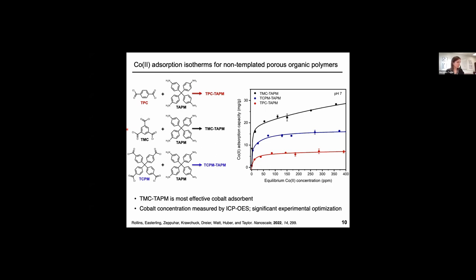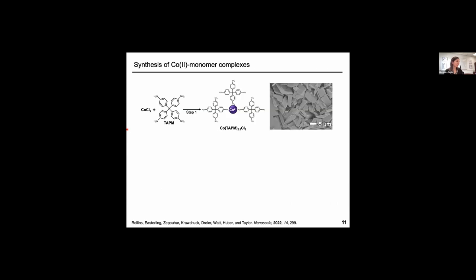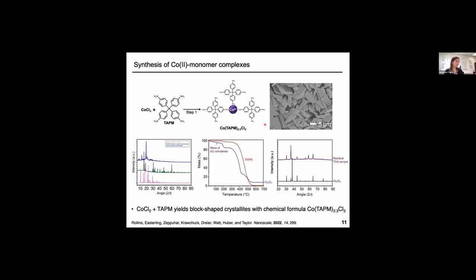I described before. So to template that polymer, we added a step at the beginning of the synthetic route in which we coordinated this amine to a cobalt 2 source. By reacting it with cobalt dichloride, we obtained these crystallites. This is an SEM of the cobalt monomer complexes. And we characterized these complexes by PXRD and TGA in order to make sure that both cobalt and the amine were present, and the correct ratio of these amino monomers to cobalt ions, so that we could then use the right amount of the subsequent acyl chloride coupling partner.